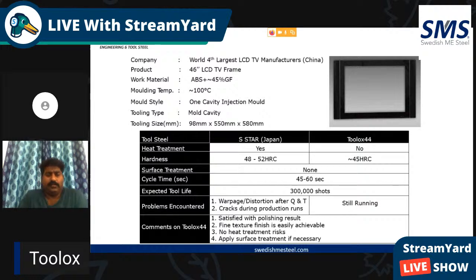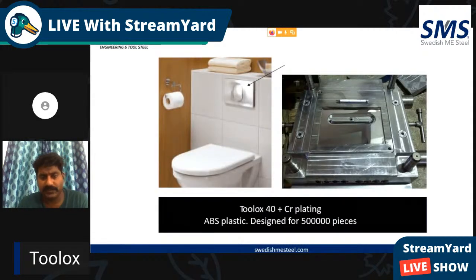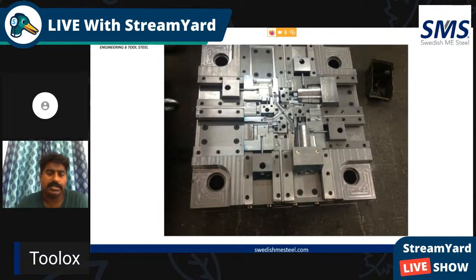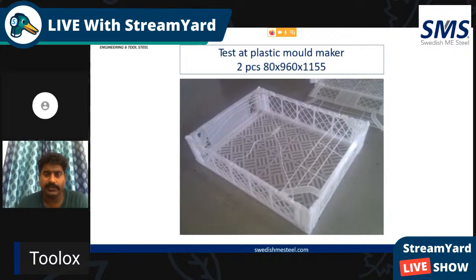So they had warpage and distortion issues after quenching and tempering, and cracks during production runs, which was not the case with Toolox 44. With all the properties it has, Toolox 44 overcame all the defects that the customers were complaining about. This is Toolox 44, Toolox 40 plus chrome plating, ABS plastics designed for 5 lakh components. That's another example for Toolox 44.